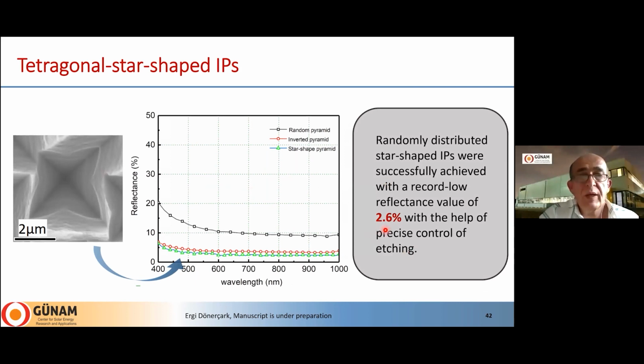We have achieved 2.6% reflection from the surface by using these tetragonal star-shaped inverted pyramids prepared by copper-assisted etching, which is a very promising technique. So we hope to use this in our different solar cell structures in the near future.